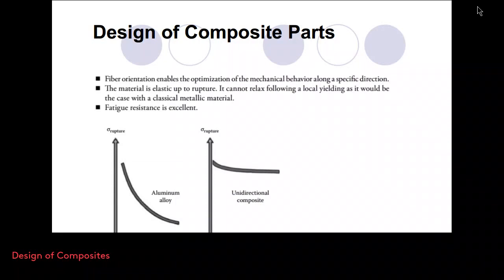When we look at the metallic materials which we use, we see that their rupture stresses decrease with the frequency of the applied load. So if you have a cycling loading, for example, and you continuously apply the load again and again, you see that some micro cracks eventually grow and load bearing capability of the structure decreases. On the other hand, in composite materials, we see that more or less the rupture stress is constant and independent of number of the cycles that are applied. Okay, so this is why we prefer composite materials in general.